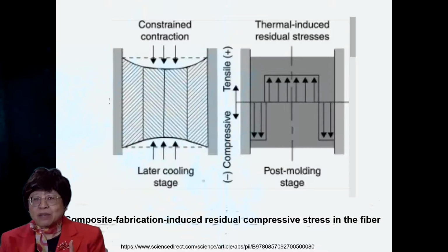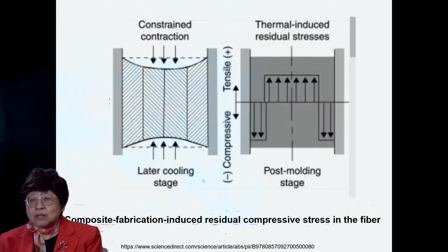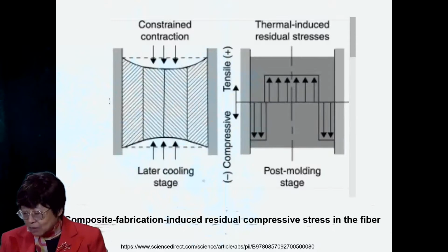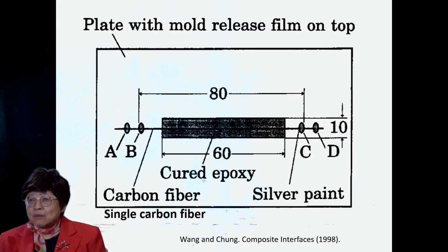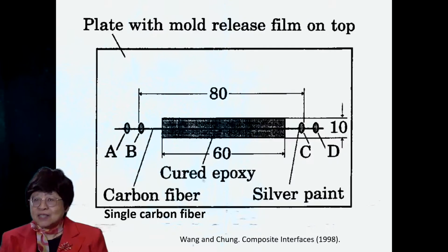And during the fabrication, particularly during the cooling part, the resin contracts, and that results in residual stress that is compressive in the carbon fiber. And one can ascertain that by resistance measurement, by taking a single carbon fiber, embedding that in epoxy, and having the two ends of the fiber stick out to provide ABCD for the 4-probe resistance measurement.